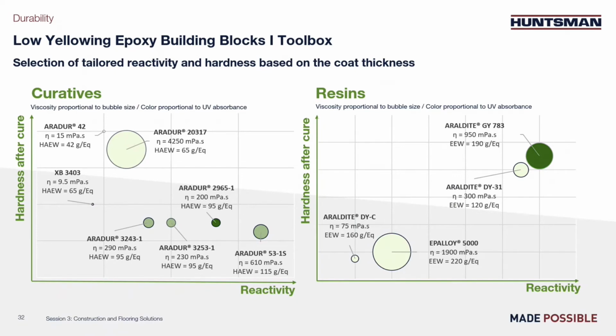For instance, the combination Araldite DY-C with Aradur 53-15 will cure okay and be relatively low yellowing, but the product will be soft, which may not be so great. The combination Epalloy 5000 with XB 3403 would be low yellowing, but for a thin film application the appearance would not be good because reactivity would be too slow.